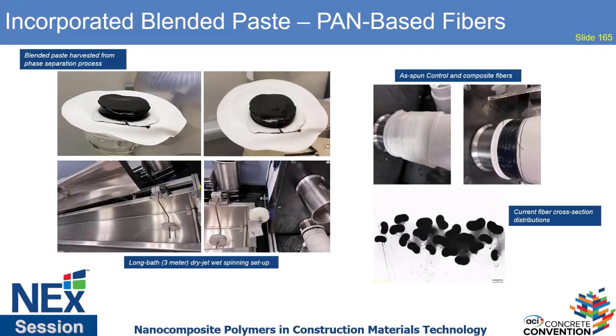So one of the things that we've been doing is harvesting this nanomaterial paste. This is what it looks like when we do the phase separation and we capture that phase of polymer that's very much interacting. It looks like this nice blob, and we're now incorporating this into our dopes in order to spin fibers. This is very challenging because we use a non-solvent in order to create this.